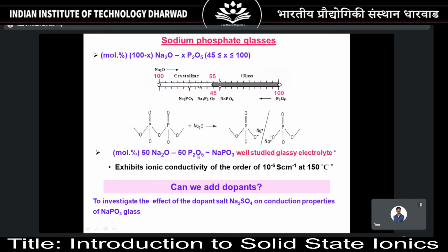Look at this composition, 50-50, because I'm interested in the 50-50 composition: 50 mole percent of sodium oxide and 50 mole percent of phosphorus pentoxide, which will give you the composition NaPO3. People call it sodium metaphosphate. If you check the ionic conductivity, it is roughly about 10 to the power minus 6 Siemens per centimeter at 150 degrees Celsius. Of course, if you just take crystalline NaPO3, it will be roughly an insulator, but when it is in a glass form, it will exhibit a conductivity of 10 to the power minus 6 Siemens per centimeter at 150 degrees Celsius.